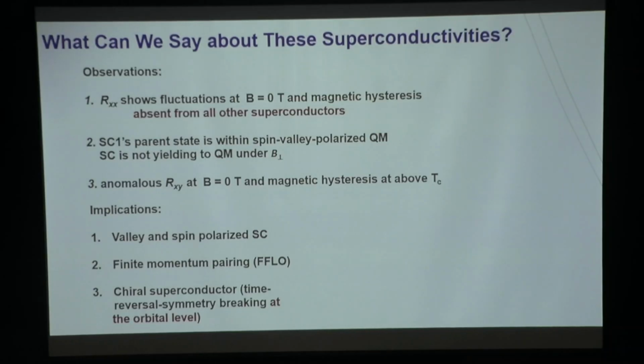And if you believe this superconductor stems from a spin and valley-polarized parent state, that has several implications. Number one, it's a valley and spin polarized superconductor, and both electrons come from the same valley, which means your Cooper pair has a big momentum, like in the FFLO picture. And you choose one of the valleys, right? And that means you spontaneously break the time reversal symmetry. And this is a chiral superconductor. The time reversal symmetry is broken at the orbital level.